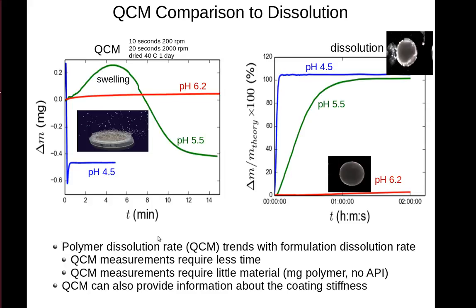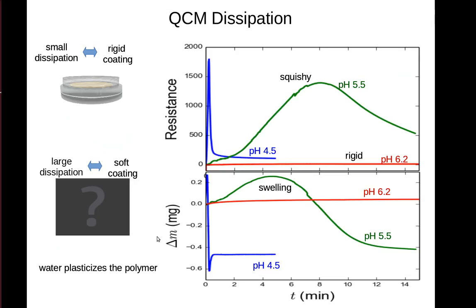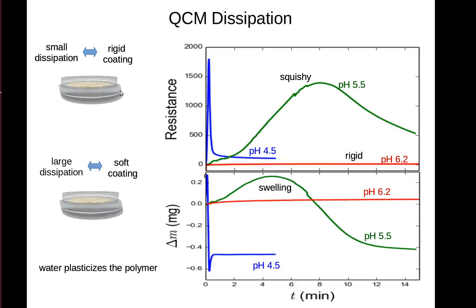QCM also provides some information about the coating stiffness. For a stiff coating, the coating oscillates in phase with the crystal, and very little energy is dissipated. As the polymer is plasticized, the film softens and oscillates out of phase with the crystal, jello-like, and dissipates energy on each oscillation. The instrument measures the amount of energy required to oscillate the crystal at the same amplitude and frequency. Thus we get some information almost rheological, such as the shear modulus of the film.